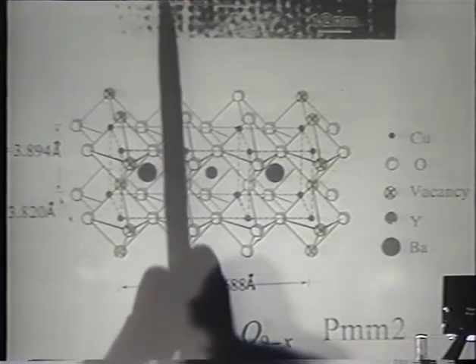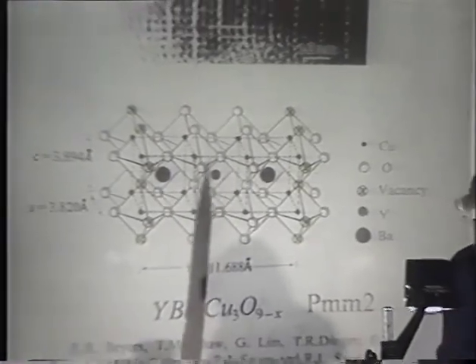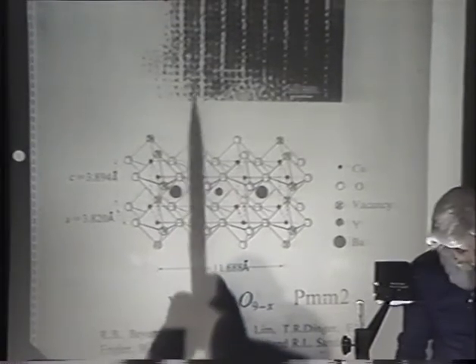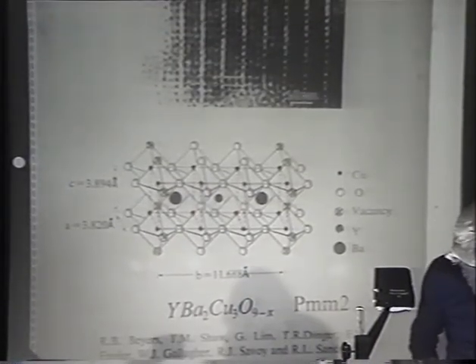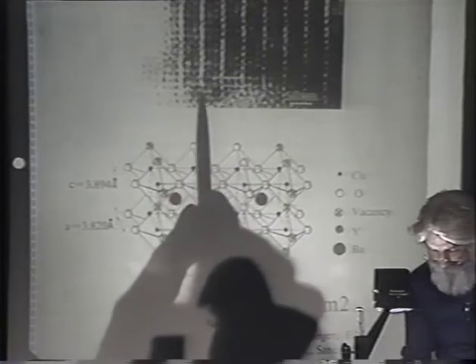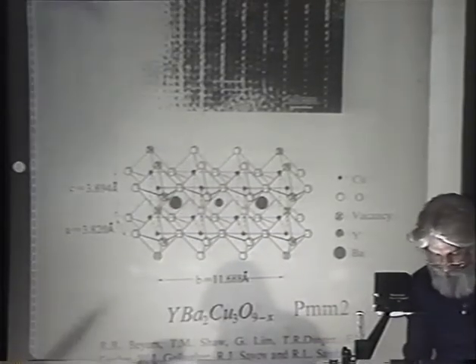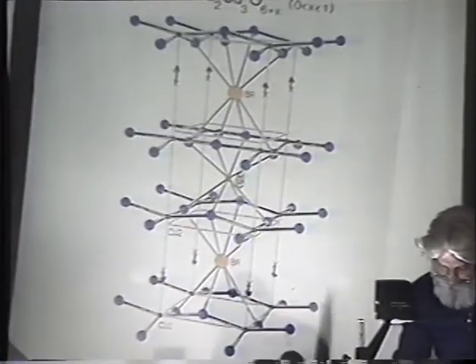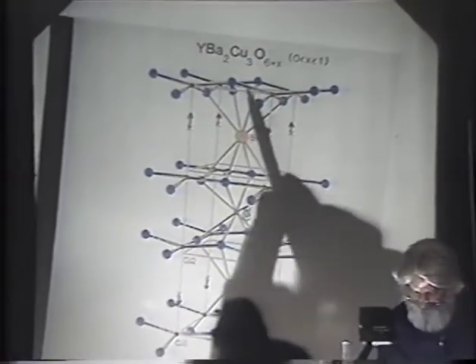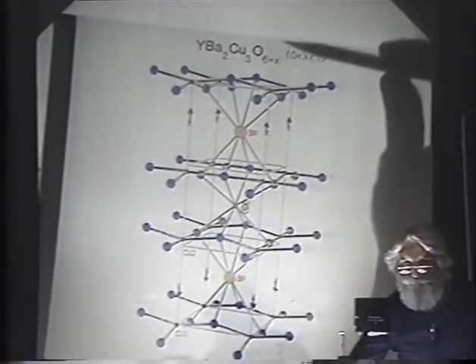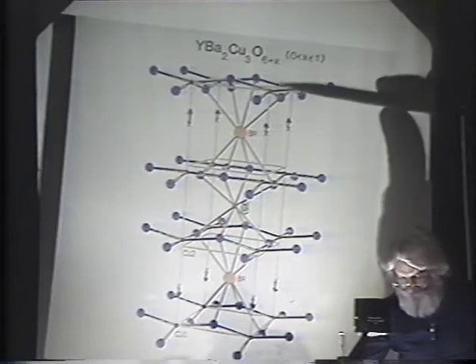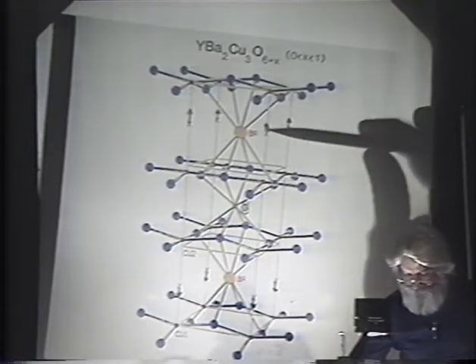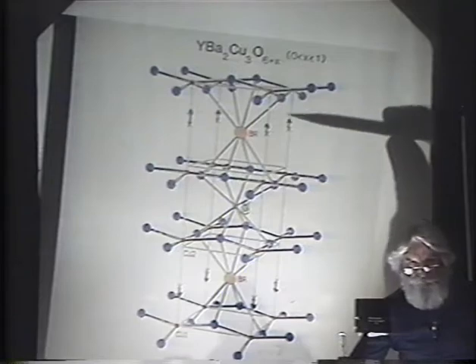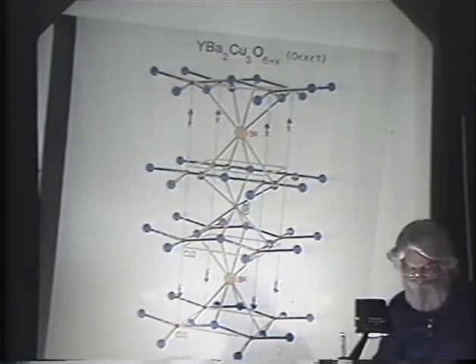What we now see from Bob Haven's nice results is that this could possibly be a reconstruction going on in the copper basal plane, opening up this white space where the electron beam just pours right through, and that what we're seeing are the copper vacancies along this line, and then a spreading of the space between the barium atoms due to this reconstruction caused by oxygens in the barium plane moving toward the copper. And I think the story is beginning to look very, very pretty in that regard.